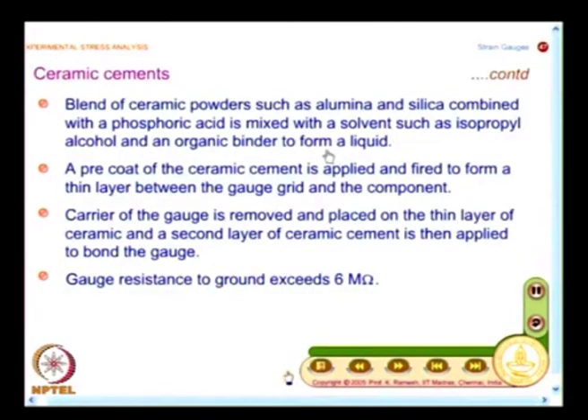And what you do is, on the specimen you provide a pre-coat of the ceramic cement. After application, it is fired to form a thin layer between the gauge grid and the component. So, it is a very elaborate process. You need to have proper training to handle this kind of special cements. So, once you form a thin ceramic cement layer on the specimen, you place the gauge, and the gauge is also very special. We will have a look at it a little while later. And you have to remove the carrier of the gauge and place it on the thin layer of ceramic, and a second layer of ceramic cement is then applied.